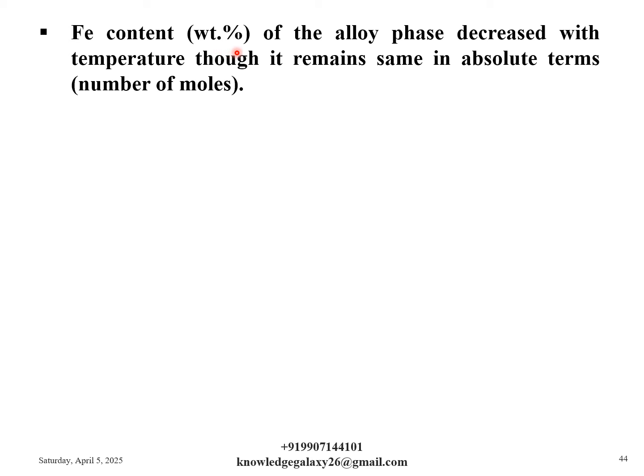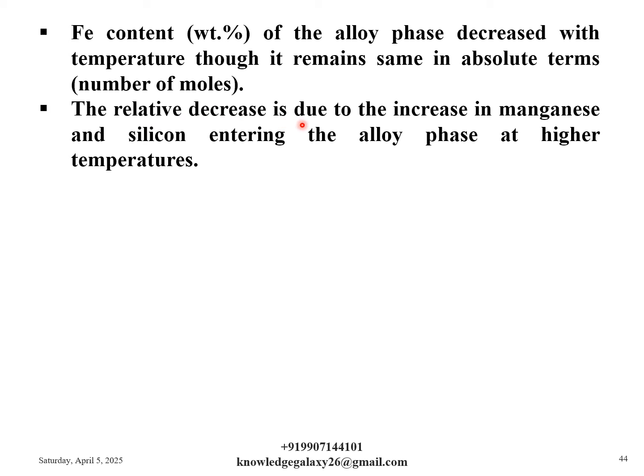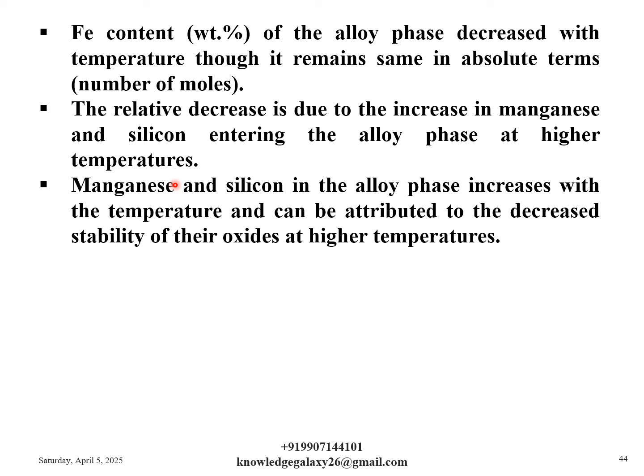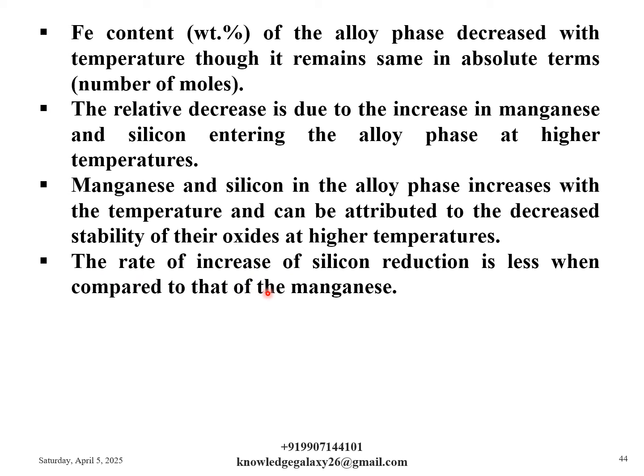Iron content, that is weight percent in the alloy phase, decreased with temperature, though it remains the same in absolute terms, that is number of moles. The relative decrease is due to the increase in manganese and silicon entering the alloy phase at higher temperatures. Manganese and silicon in the alloy phase increase with temperature and can be attributed to the decreased stability of their oxides at higher temperatures. The rate of increase of silicon reduction is less when compared to that of manganese.